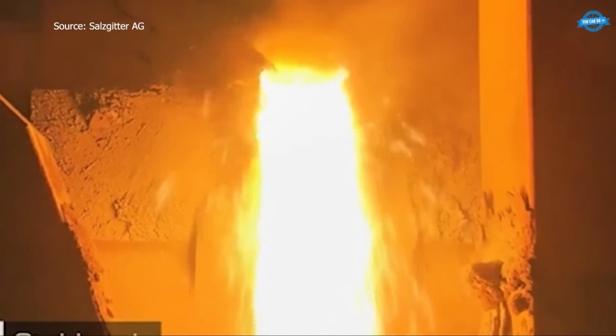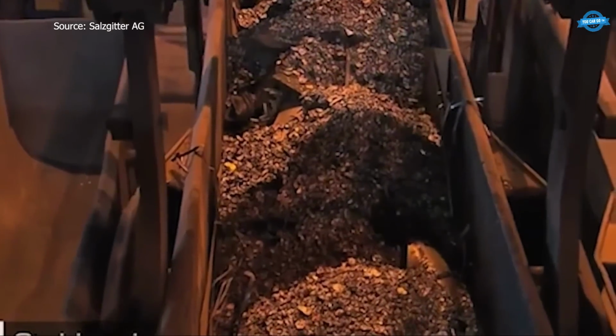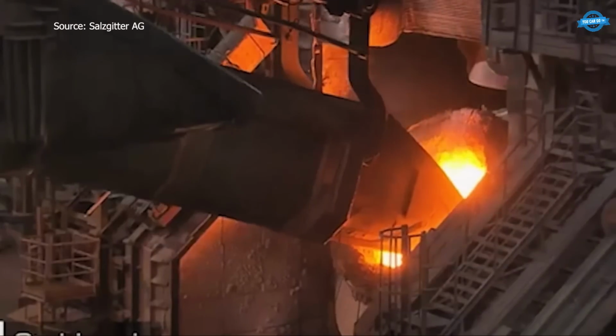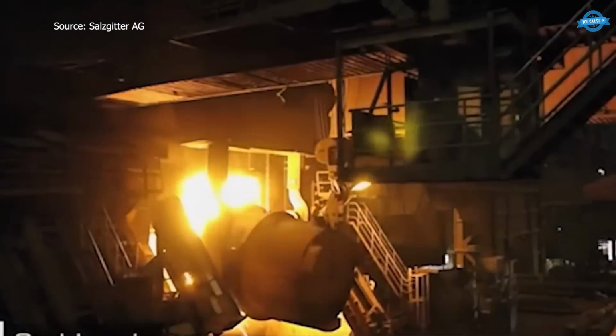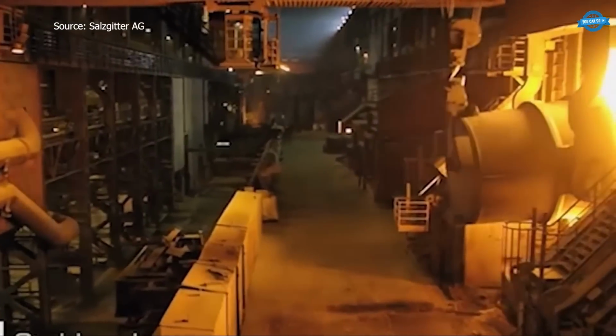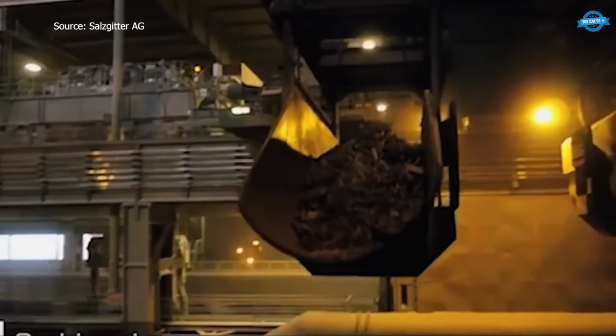The molten iron flows into torpedo ladles and is then transferred to converters, where pure oxygen is injected to remove impurities. Scrap metal is added for cooling, stabilizing the converter temperature around 1,700 degrees Celsius. This blowing process transforms iron into crude steel, up to 12,500 tons per day.